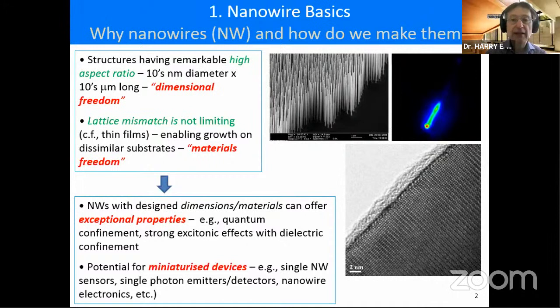Secondly, if you look at that same picture, that SEM micrograph with the long hairs sticking up, you'll see that the nanowires you're looking at are actually indium arsenide. The substrate's gallium arsenide, and those are highly mismatched. It's over 7% mismatched, and clearly lattice mismatch is not a limiting factor there. So in fact one can grow quite dissimilar materials on each other. So that means that one has a materials degree of freedom in these systems. You have both a dimensional degree of freedom and a materials degree of freedom in these nanowire systems.